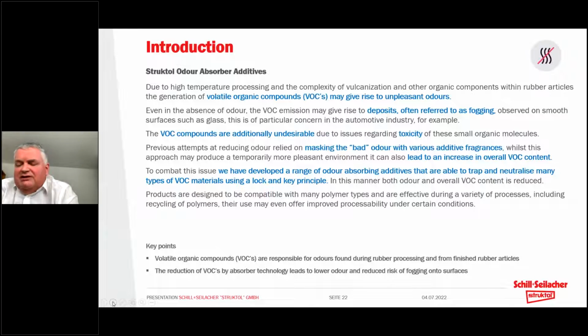Previously, the attempts to work on this, at least from an odor reduction point of view, have largely involved masking the bad odor with some kind of additional odor, a fragrance, if you like. So we would say these are odor masks rather than odor absorbers. Whilst this might give you a more pleasant environment, ultimately we would get an increase in the overall VOC. So we would have the bad odor and an additional pleasant odor, perhaps something like vanilla essence or peppermint oil or orange oil, which would contribute to hopefully an overall more positive smell, but the VOCs would be higher. Really, to combat this issue in a different way, we have odor absorbing additives that are able to trap and neutralize many types of VOC materials using a chemical lock and key principle. In this way, both the bad odors and the overall VOC content could be reduced. Next slide, please.